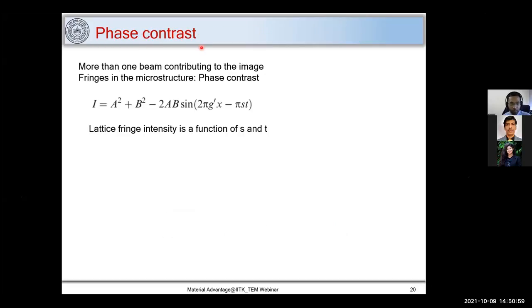Now let me come to phase contrast. Phase contrast can be obtained when I consider two or more beams. In the earlier image, I just considered one diffraction spot, but in this case, if I consider more diffraction spots, I can form an image, and that contributes to phase contrast. So here, this equation indicates that the intensity, you can just see this part, is proportional to, sinusoidally varying with respect to S, which is the deviation parameter, and T, which is the thickness of your sample.